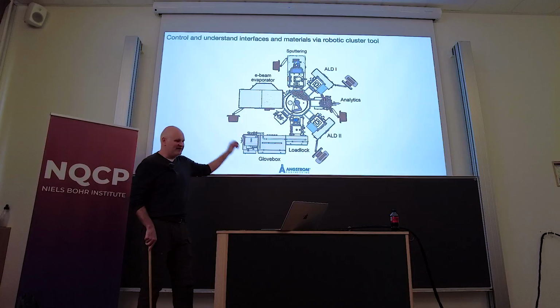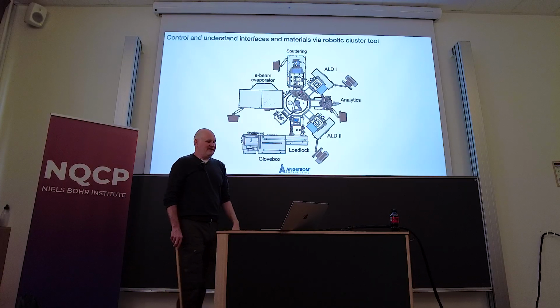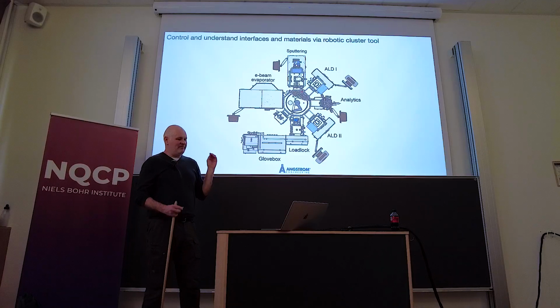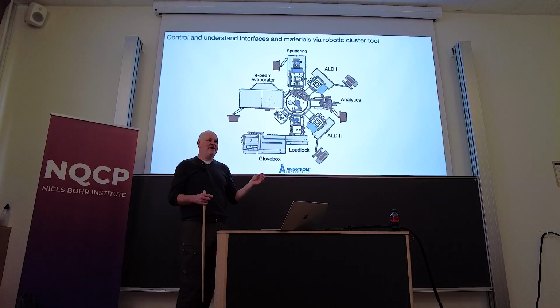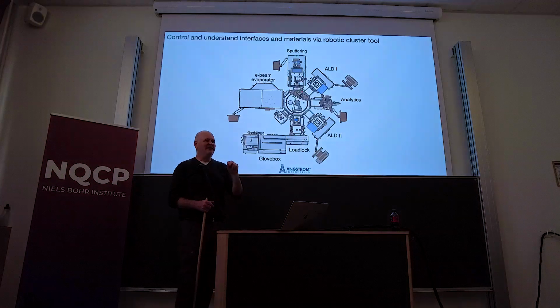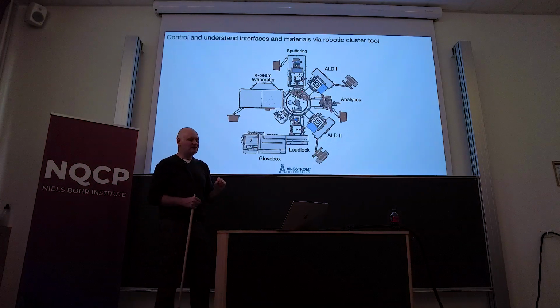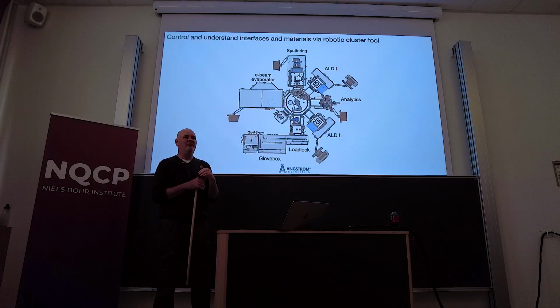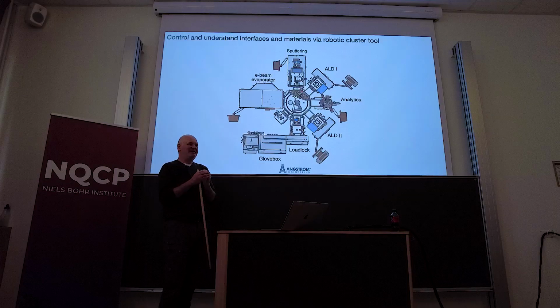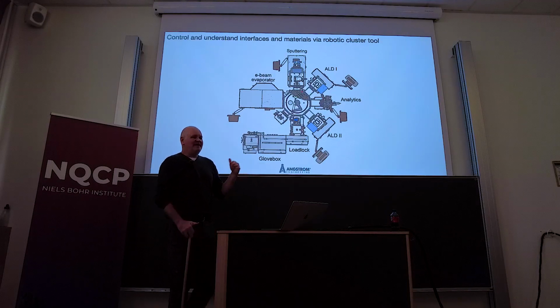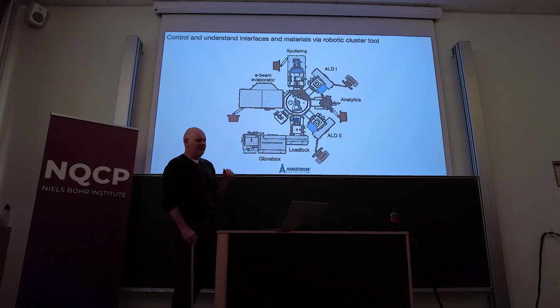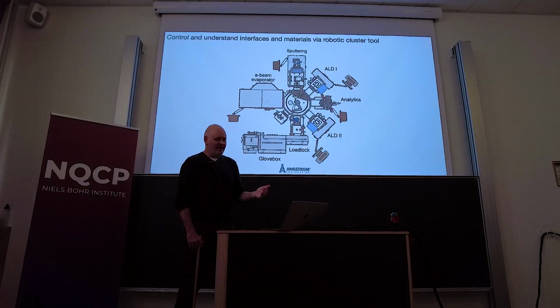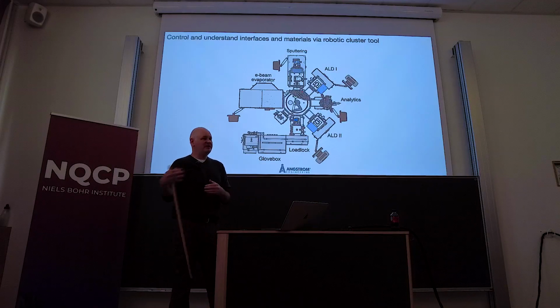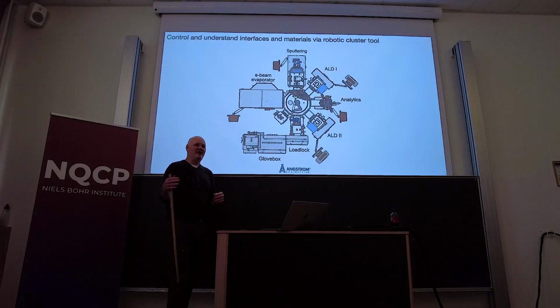Okay, so the cluster tool. Essentially what I wanted to build was a system that would allow me to do different kinds of growth and different kinds of fabrication of materials, stacking materials one on top of the other without breaking vacuum so that we could build interfaces that were clean, but also include analytics so that we could actually look at interfaces, we could modify interfaces and have feedback between them. And so, with that in mind, also explore new materials, so not just conventional tantalum and niobium and aluminum,